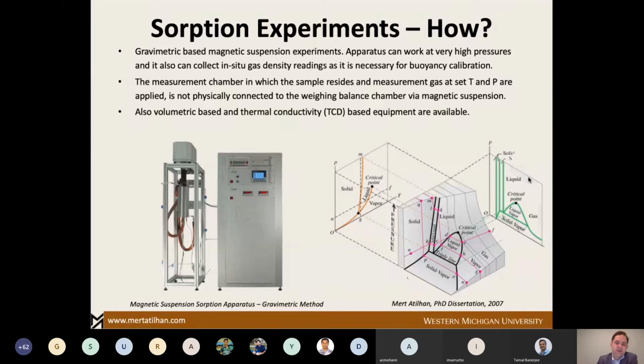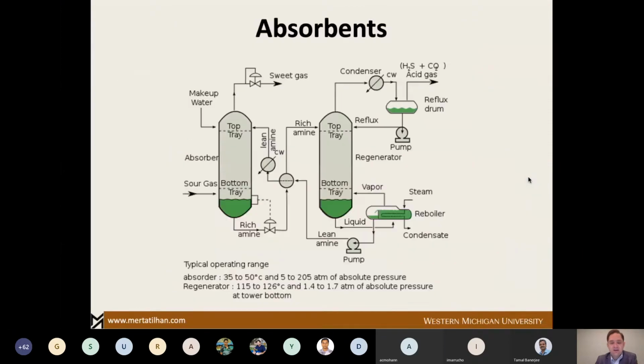So you see the weight increase in live mode. In situ mode, you can observe what's going on in the cell in terms of adsorption or absorption. This technique also gives you another flexibility: in case of swelling, you can see it directly, because the gravimetric method is affected by the volume of the sample. In case of swelling, your volume will be expanding, so you have a sudden drop in the buoyancy, which means you will have a direct observation of the swelling effect.